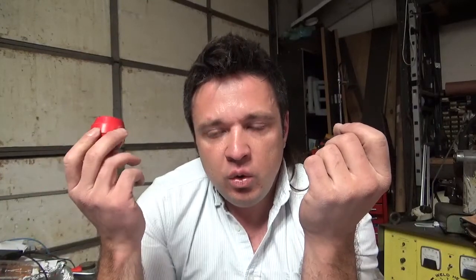So how are nanotubes made? Well, the basic premise is this. You start with a metal catalyst, and you would need one of a small size, perhaps a few nanometers for single-wall carbon nanotubes, and you place this into a carbon-rich atmosphere. Then the free-floating carbon vapor would be absorbed by a droplet here. Then it would be ordered and form a cap coming out of this droplet. And then this droplet would act as a machine, taking the free-floating carbon vapor, adding to this cap, thereby growing an ordered nanotube.